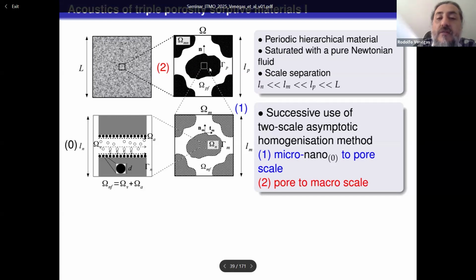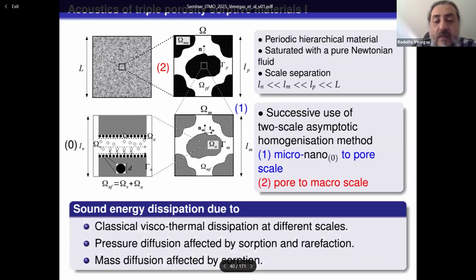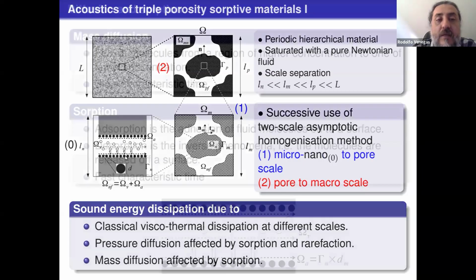And then we couple that representation with the Navier-Stokes system formulated around these grains, and we applied again homogenization to get a macroscopic description of wave propagation in this medium. We will see that some energy dissipation is due to classical viscothermal dissipation at different scales, pressure diffusion affected by sorption and rarefaction. Rarefaction is a phenomenon that appears in pores that are compatible with the mean free molecular path, and mass diffusion affected by sorption, which is the process whereby these molecules are transported from these pores into these nanopores. And sorption is a process that I will stop a little bit to talk about in more detail here.